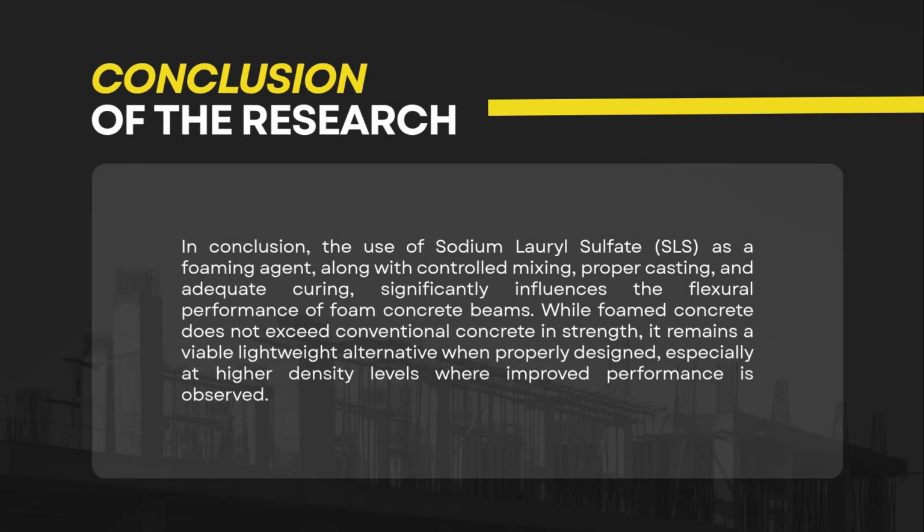In conclusion, the use of sodium lauryl sulfate as a foaming agent, combined with controlled mixing, proper casting, and adequate curing, plays a crucial role in the flexural performance of foam concrete beams. Although foamed concrete does not surpass conventional concrete in strength, it offers a viable lightweight alternative when properly engineered, particularly at higher density levels.